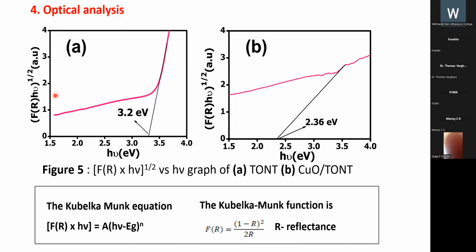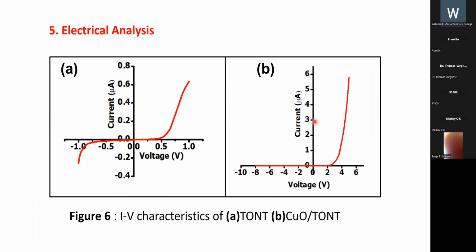This is the optical studies. Diffuse reflectance spectroscopic analysis is done to determine the optical bandgap of the sample. Optical studies in figure 5 indicate a reduction in bandgap from 3.2 electron volts for anodized TONT to 2.36 electron volts for the modified structure.